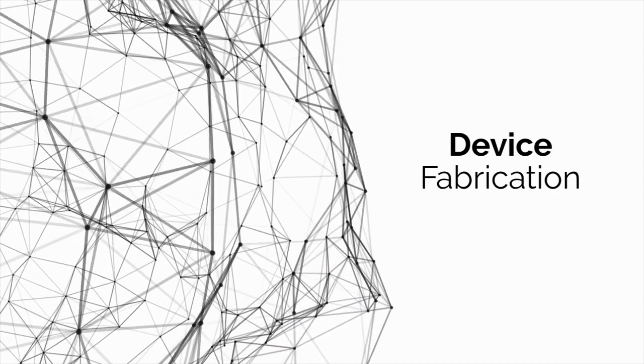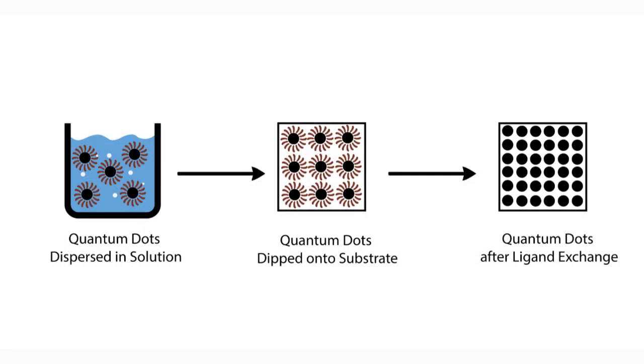When fabricating a quantum dot thin film device, quantum dots are first dispersed in solution. Then by dip coating, we deposited the quantum dots onto a substrate. After the device is dry, we again dip the device into a ligand exchange solution, replacing the long ligands with short ligands, bringing the particles closer to each other and thus allowing electrons to transport across particles, which makes the device conductive. By repeating the process to a certain extent, we optimize the conductivity and the responsivity of the device.